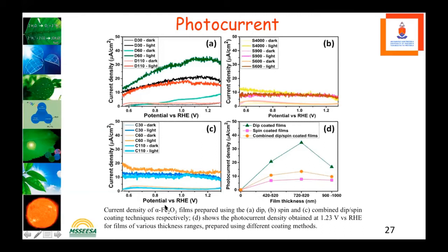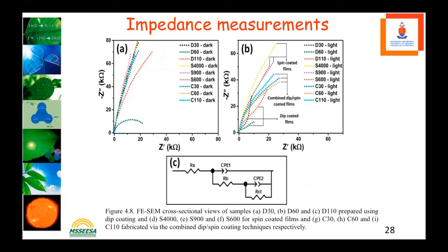So the current density of iron oxide prepared using a method called dip coating, comparing it with spin coating, comparing it with both dip coating and spin coating. And we're able to find that there is an improvement, and we chose this dip coating. Why dip coating? Because when you dip the substrate into the solution, it makes a rough surface, a rough morphology, which is very good for the solution to penetrate the hematite in such a way that your photocurrent is improved. We have done impedance measurements.